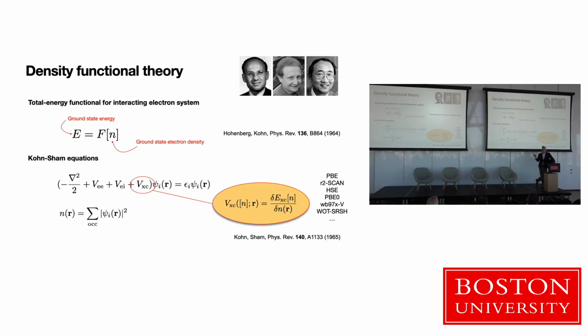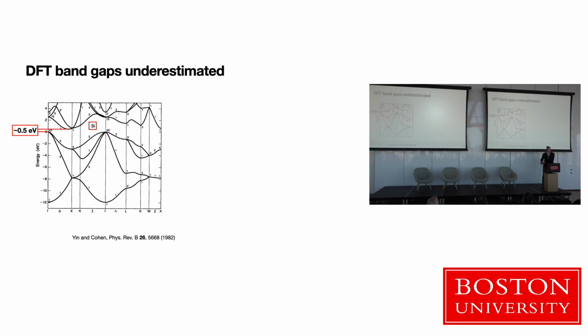Basically, there are different classes of exchange correlation functionals, which are the approximations, and some are generalized gradient, semi-local, and some are hybrid functionals. These hybrid functionals include some exact exchange. Now, the DFT band gap, as has been pointed out, the gap computed from some of the quantities that come out of a DFT calculation, is underestimated, and there's good physical understanding of that. This is I think the first calculation of DFT band structure for silicon. Yes, that reference is 1982. That's exactly what it is.